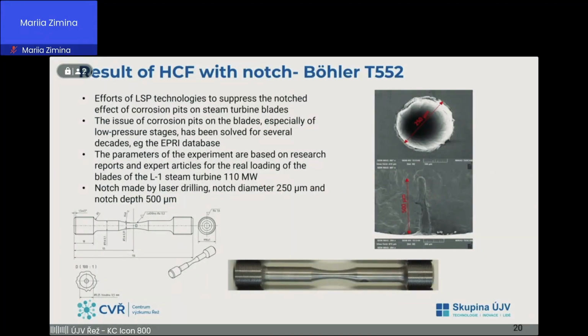Okay, and the last results are from an experiment of high cycle fatigue on material for turbine blade, Böhler T552. The goal of the LSP treatment is to suppress the notch effect of corrosion pits of steam blades. The issue of corrosion pits on blades, especially of the low pressure stage, has been studied for several decades. The parameters of the experiment are based on research reports and expert articles for real loading of the blades of an L-1 steam turbine, 110 megawatts.